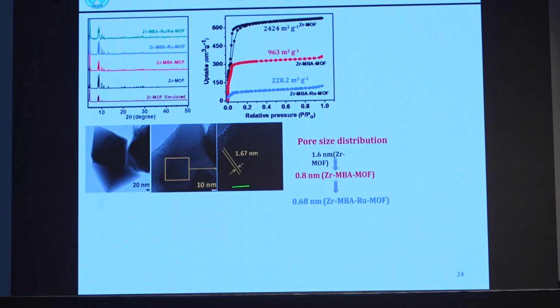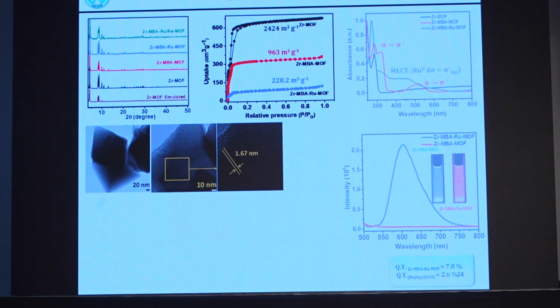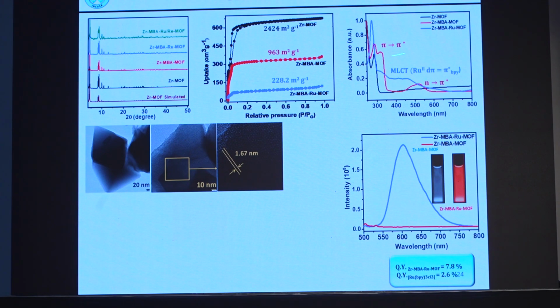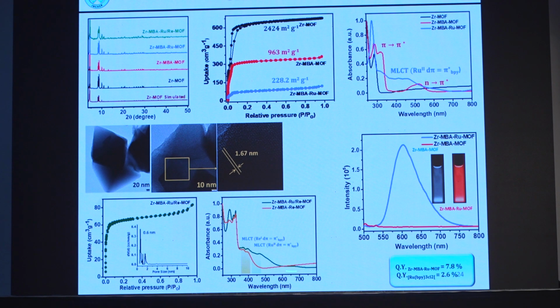To characterize it, we do a lot of characterization, I'm not going to bother you much. So this is the one, so that the MOF structure remains intact here. So you have that octahedral crystal morphology, and high resolution HRTEM shows the 1.67 pore size. When you post-synthetically modify it, automatically your surface area should decrease, and it is decreasing from 2424 to 963, 228.2. So now you see, after that when you incorporate, the original MOF was not emissive, but when I put the ruthenium, it has become emissive because of the MLCT absorption, okay? So quantum yield is very high. When I put the rhenium, it further decreases the surface area, and there is a rhenium MLCT band.